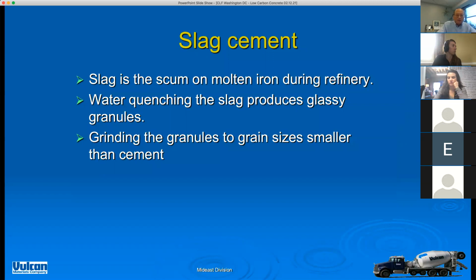Okay, I want to give you a little bit of detail about what each of these materials is. For those who are unfamiliar, we'll start off with slag cement. Slag comes from steel or iron refineries. When you take iron ore and melt it to refine it, you have a lot of impurities, and those impurities float on top of the molten iron. That's really the scum floating on the molten iron, and that's slag. You divert that slag, separate it from the molten iron, and then quench it with water, meaning pouring lots of water on it.